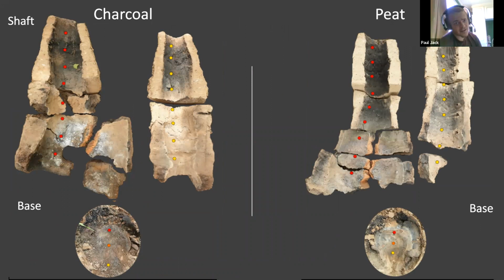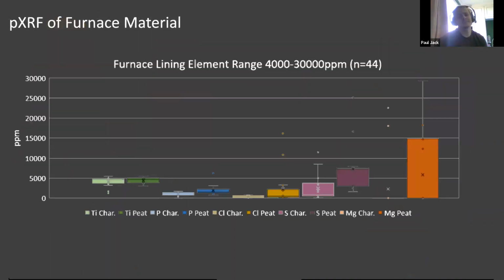I also took the XRF analysis of the furnace material, as I said. Each red dot here is a reading from the back of the furnace, from where the tuyere is, and each yellow dot is from the front of the furnace, where the door is that we cracked open to retrieve the bloom. And unlike the slags and the blooms, this produced quite substantial differences in the chemical composition between the two sets. Most notable here in the sort of 4,000 to 30,000 parts per million range. Titanium, pretty similar, but we've got a slight elevation in phosphorus and chlorine, of sulfur, but also magnesium in the furnace material that's been exposed to the peat fuel.